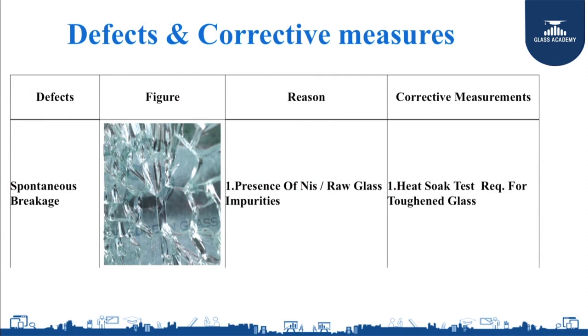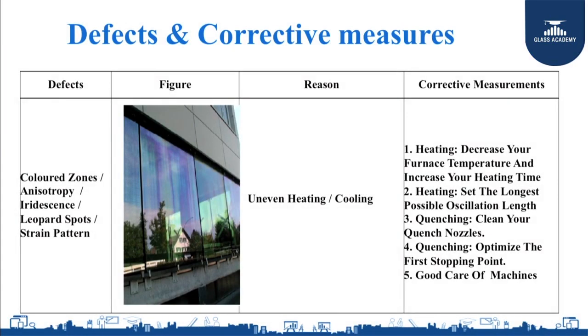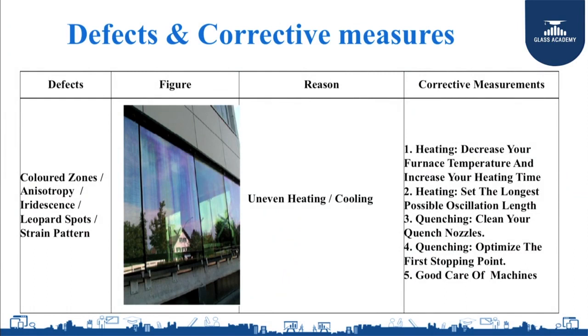Spontaneous breakage. Reason is very simple. Presence of NiS in raw material. Corrective measure is a heat soak test can be done so that spontaneous breakage is avoided. Now colored zone, leopard spots or strain pattern. Reason is simple, uneven heating or cooling. Decrease your furnace temperature and increase your heating time. Set the longest possible oscillation length. Clean your quench nozzles. Optimize the first stopping point. And of course, good care of the machine.